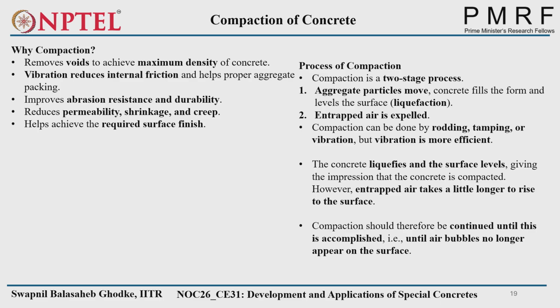Compaction can be done by rodding, tamping, or vibration, but vibration is more efficient and popular. So concrete liquefies and the surface levels, giving the impression that the concrete is compacted, but it is not actually compacted because entrapped air takes a little longer to rise to the surface. So you have to do compaction until this is accomplished, that is, until air bubbles no longer appear on the surface.